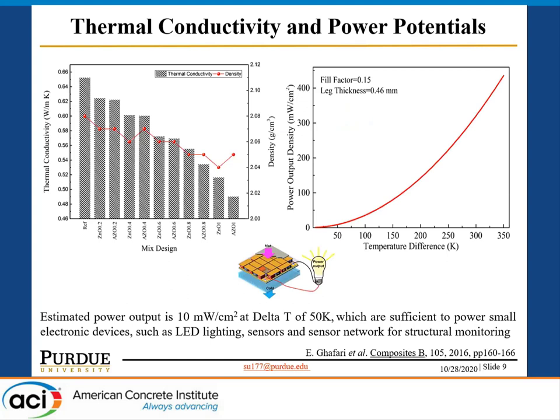And as I just mentioned, we need to have lower thermal conductivity to have higher efficiency for the energy harvesting. So the thermal conductivity result I show on your left hand side is a mixture design versus the thermal conductivity, and as you can see, the thermal conductivity decreased with the increase of the addition rate of the nanoparticle.